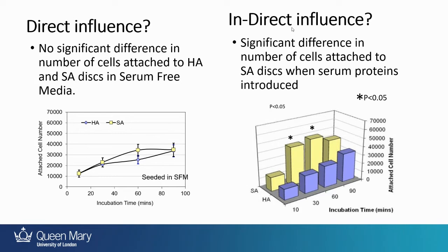And we found that if you just looked at cell attachments to different materials, so the blue is without the silicon and the yellow is with the silicon, there was absolutely no difference at all in cell attachment in serum-free media, so media without any of the proteins. As soon as you introduce serum proteins to the environment, which is what you're going to actually have in the body, there was a massive difference between cell attachments. So the cell attachment on the silicon SA was much higher.